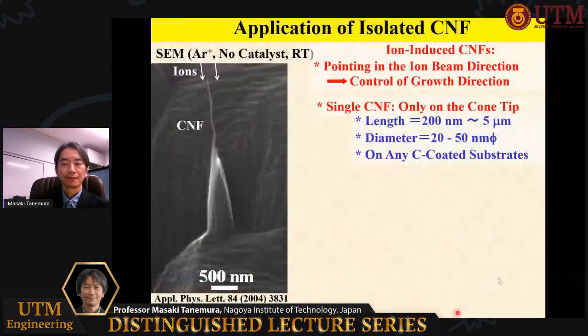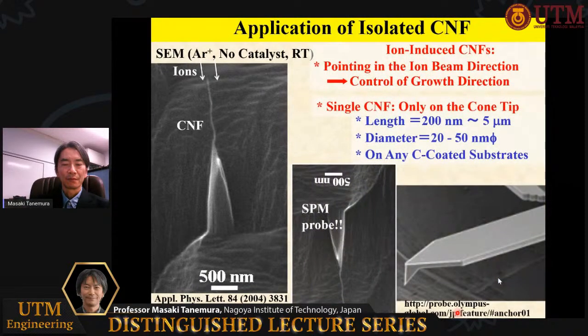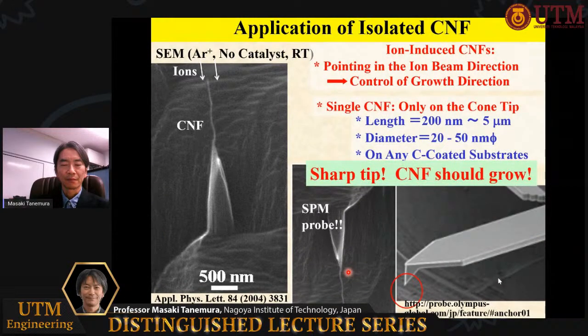The carbon nanofiber on the AFM cantilever was prepared like this. If we turn this picture upside down, this reminds us of the AFM probe. The carbon nanofiber grows only on the sharp tip. AFM probes have a sharp tip originally, so the carbon nanofiber should grow on it. And the carbon nanofiber grows in the ion beam direction. This means we can control the growth direction. So let's try.